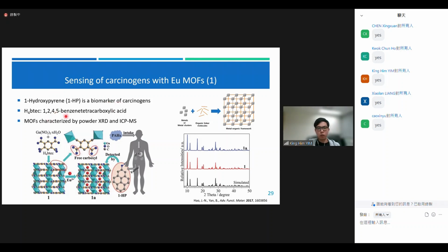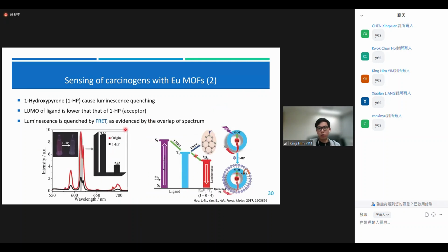This time they use this benzenetetracarboxylic acid as the ligand, to form a 3D MOF network with Eu. And this MOF is characterized by powder XRD and also ICP-MS. Then they try to use this MOF for sensing 1-HP. The presence of 1-HP caused the luminescence quenching of this Eu MOF. Here shows the luminescence spectrum of the compound. The red one is the original MOF. It is highly emissive, but upon the addition of 1-HP, the luminescence dropped significantly.